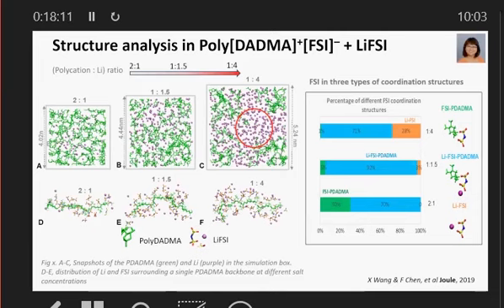So what Fang did here was set up a simulation box using, I think it was Gromacs in this case, with a number of poly-DADMA chains, roughly 12 or so monomer units long, so not super long, but long enough. And then she was adding different amounts of salt and looking at the conformations, the structures in these MD simulations, and trying to understand if there was a correlation between these and what we were observing in the data.